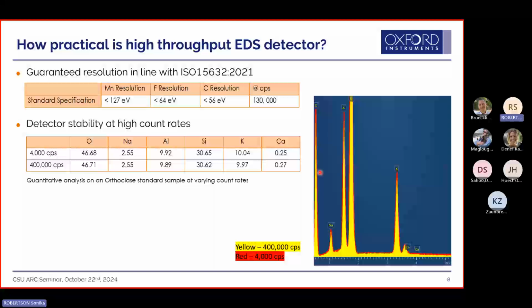What's called sum peaks. I don't know if you've run into those at all, but there are nuances when you're doing the analysis. So historically, with high throughput, you could crank up the voltage and the beam current and get higher throughput, but could you process it? Your dead time goes through the roof and you end up saturating the system.